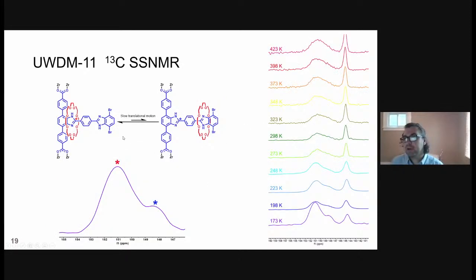So we went back and, for UWDM11 with mesitylene in the pores, we remeasured the carbon-13 solid state NMR. And we can see when we go down to 173 Kelvin now, we get two peaks: a smaller peak upfield and a larger peak downfield, corresponding to this carbon-13 enriched position. The downfield peak, as we know from solution, corresponds to the bound recognition site, while the upfield peak corresponds to the unbound recognition site.